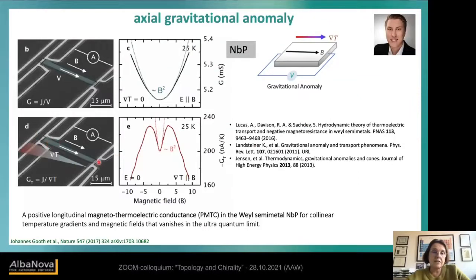the gravitational anomaly. So we applied a thermal gradient on top, and this is quite challenging in these small nanoribbons at low temperature. But here you can see the prediction exactly from Landsteiner and from Sachdev was that this should be a B square behavior at low field, and then if you go to higher field, it changes direction and should go versus zero, the thermal conductivity.